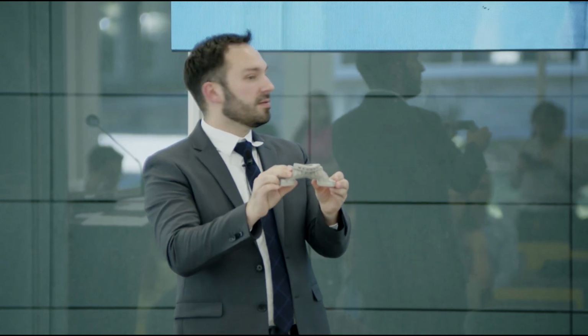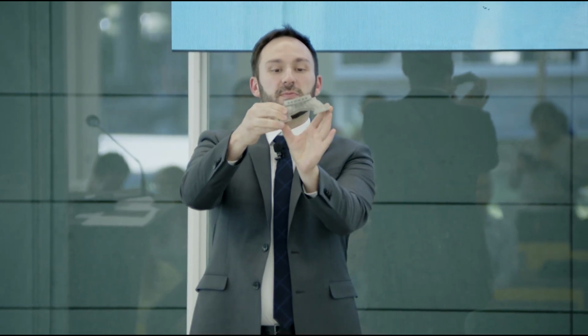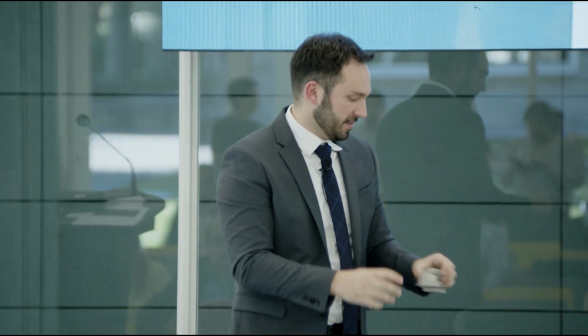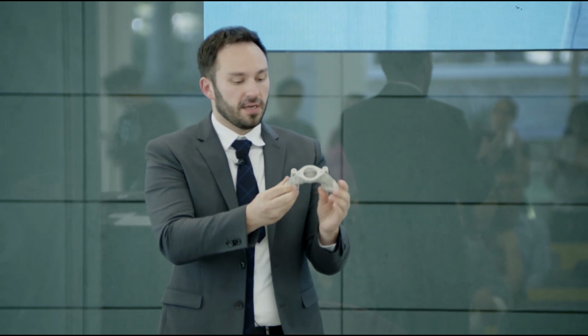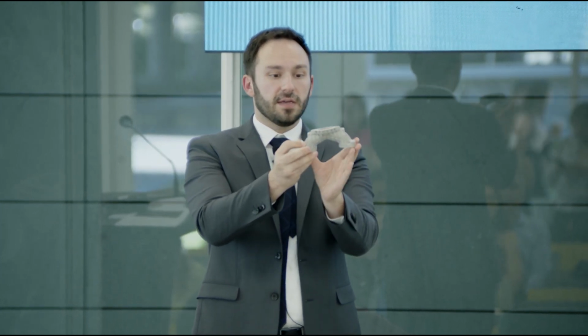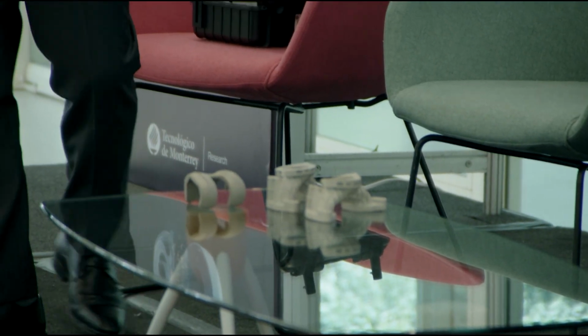So I think it's probably easy enough to see that these legs splayed out. There was a body load that actually caused these legs to splay out. Oh, yes, perfect. So these legs have splayed out, and then on top of that, this top flange here has kind of gone into potato chip mode. So this was no attempt at compensating the part before it went in the furnace. The second one I have was run through AMP, which is built on GE data as we're developing these sinter cycles. And so you can see that these legs are no longer splayed out and that this top flange is nice and flat. So part of the reason to use AMP is to make those very large scale components. And we can head back to the slide deck if you would.